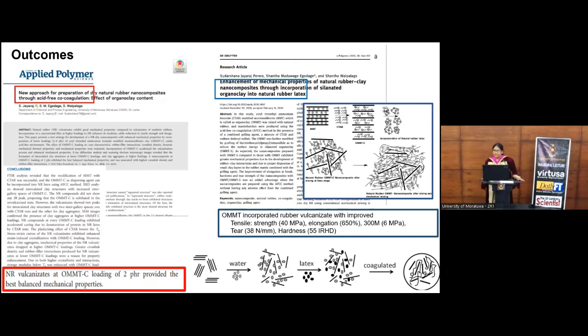The outcomes of my research: we found a new method to produce nano clay composites starting from natural rubber latex. That was successful. The clay is first made into a dispersion, and this aqueous dispersion is incorporated into liquid latex, and then the clay exfoliated structures are formed. Then the liquid nano composite is dried or coagulated in situ. The clay is dried as well as the rubber becoming a dry form.